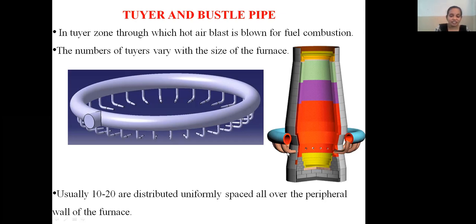Around 1200 to 1300 degrees Celsius temperature is maintained in the preheated blast of air. This air is preheated in the stove. Through the stove, the bustle pipe is connected to the blast furnace, encircling the peripheral wall of the furnace, and these tuyeres are connected to the furnace with tuyere nozzles. Through this nozzle, preheated blast of air is injected into the blast furnace under pressure, with the air temperature maintained around 1200 to 1300 degrees Celsius. In the tuyere zone, hot air blast is blown for fuel combustion.